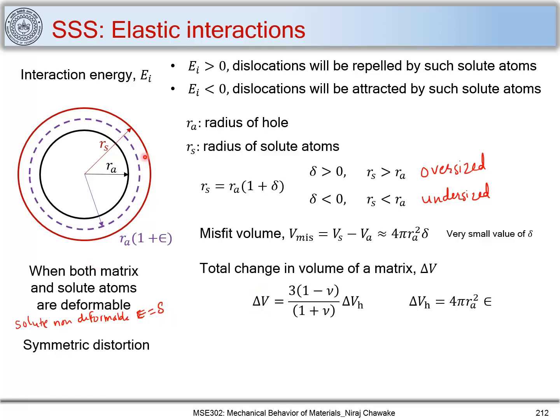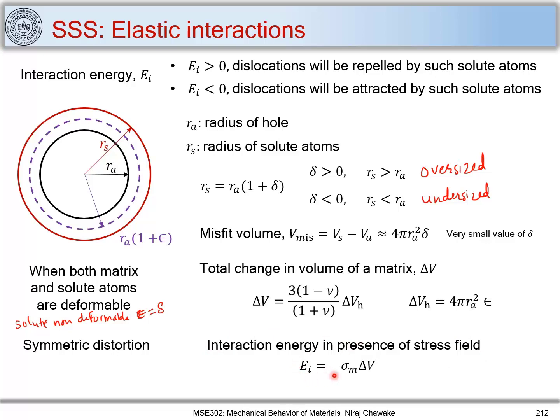When we put the solute atom into the hole, we consider there is a symmetric distortion. This distortion leads to interaction energy with dislocations in the presence of a stress field. This interaction energy is Ei = −σm · ΔV, where σm represents the hydrostatic stress field. Because the distortion is symmetric, it has only a hydrostatic component and no deviatoric component, so it interacts only with dislocations having a hydrostatic stress field.